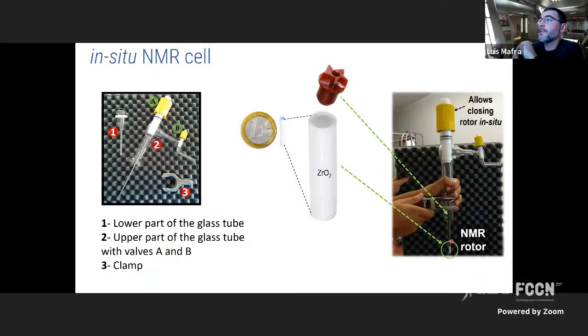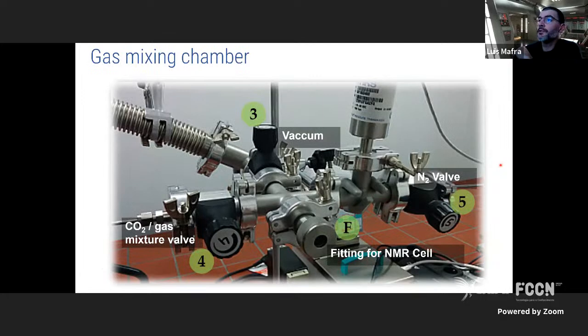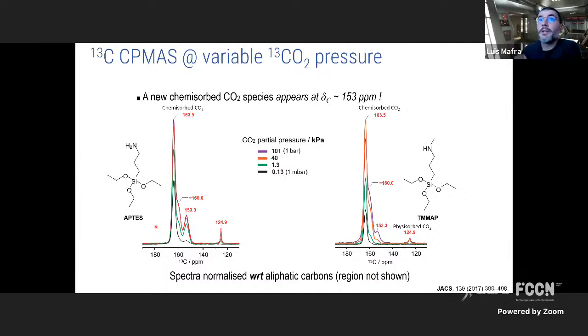So this NMR cell that you see here on the right then is hooked to this front side here. And of course you have then the nitrogen valve, because if you want to do partial pressures below ambient pressure, then you have to fill it up to 1 bar with an inert gas. You have the vacuum pump, and you have then another inlet to add a second gas if you want, or just a mixture of gases. This is a general apparatus. So carbon spectra are as follows.